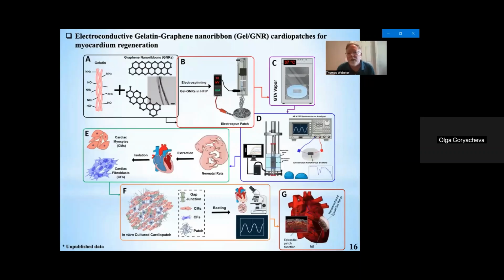So now moving on to cardio patches, same idea. We can use these nanostructures. Here's graphene nanoribbons. But as I mentioned before, we've also used gold nanorods, which are also conductive, and carbon nanotubes, which are conductive. We used a series of conductive nanomaterials and then combine them with a gel matrix. Here I'm going to show you results on gelatin, but we've also used GelMA. We've used other kinds of hydrogels that are currently being used in medicine. Make a composite out of those materials.